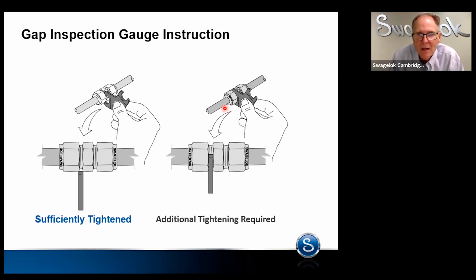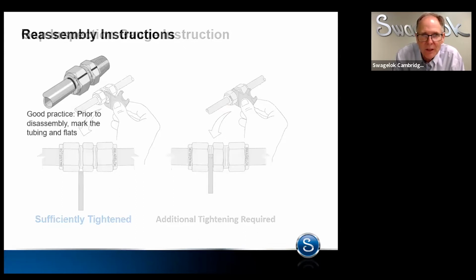You get a wide variance of a tolerance band. We machine our ferrules from bar stock and hold our tolerances within 1,000th of an inch. The end result is we have a very predictable dimension when you make it up. Therefore, we can create a gauge and make it up. It's a testimony to the tight tolerances and the materials that we utilize that we're a gaugeable tube fitting.